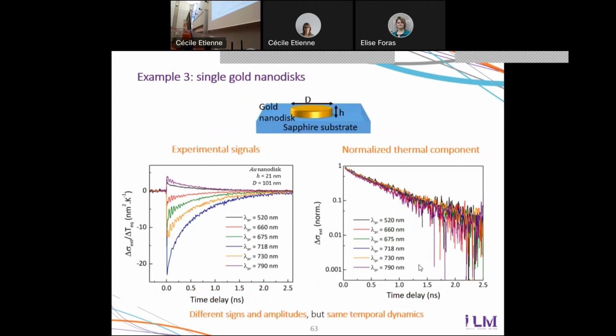Another system that we investigated is the same as that I discussed for the vibrational studies. It's gold nanodisk on sapphire. So here, changing the wavelengths changes a lot the amplitude of the signals, but not their shape. This actually means that we are never sensitive to heating of the sapphire. Here we are only sensitive to heating of the gold nanodisk, and this heating translates with a very different efficiency into an optical signal.